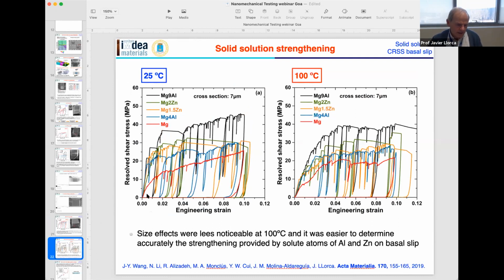The red line here corresponds to pure magnesium, and then you have lines in different colors. Blue and black correspond to magnesium aluminum with different aluminum contents, and orange and green correspond to magnesium zinc with different zinc contents. You can see very clearly here the strengthening effect of solid solution on the critical resolved shear stress for basal slip. In the case of the tests carried out at high temperature, of course, the size effects were less noticeable, and it was easier to determine accurately the strengthening provided by solute atoms of aluminum and zinc on basal slip.